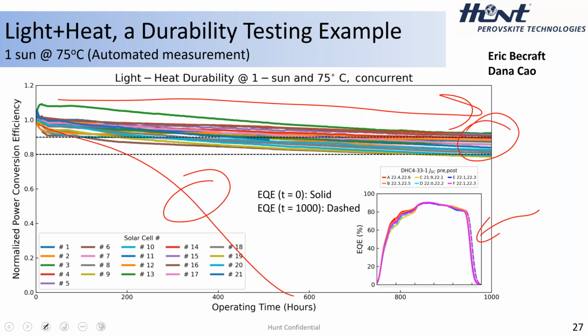And so you can see the solid lines are the spectral response of the device before testing, before light plus heat testing. The dashed is after. And you can see that the dash and the solid more or less superimpose. The integrated current densities highlighted here in milliamps per centimeter squared are virtually identical. Some actually go up a little bit, but the material is maintained. We're not actually showing any degradation of the perovskite material. The current density is maintained from time 0 to time 1000.